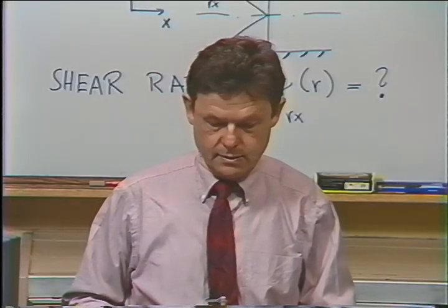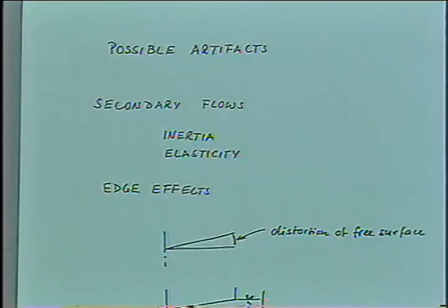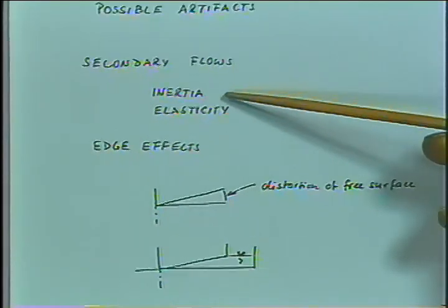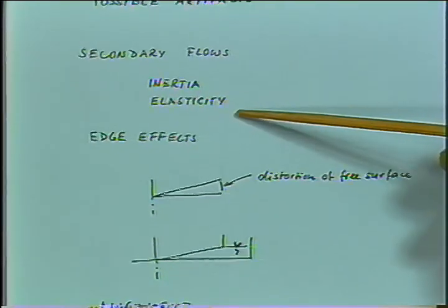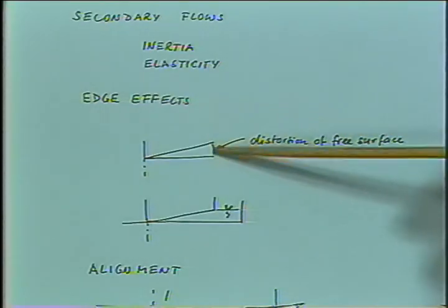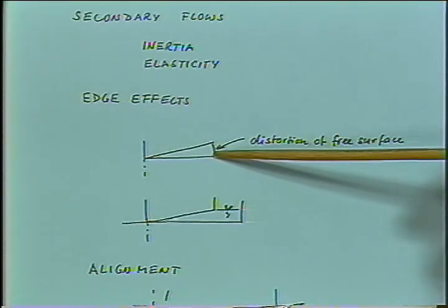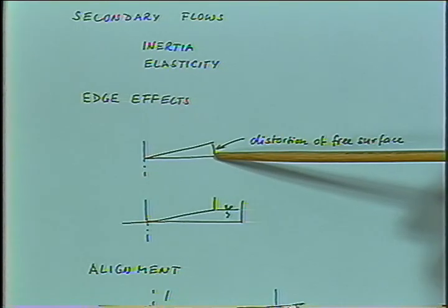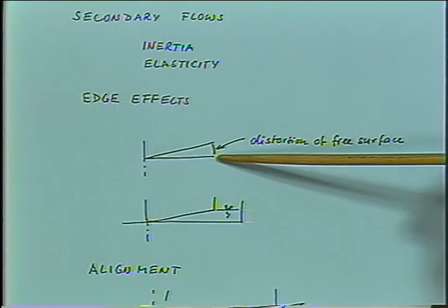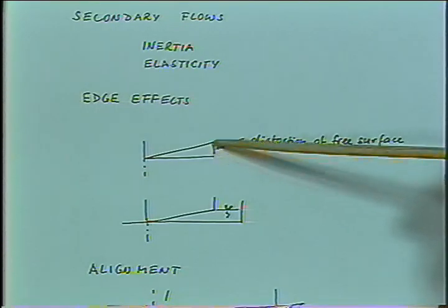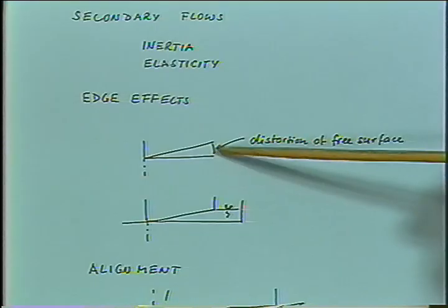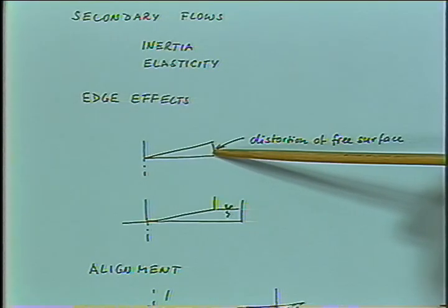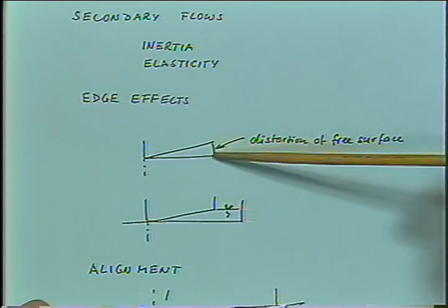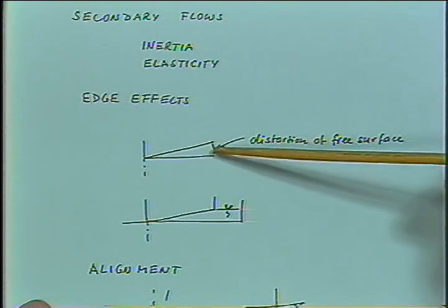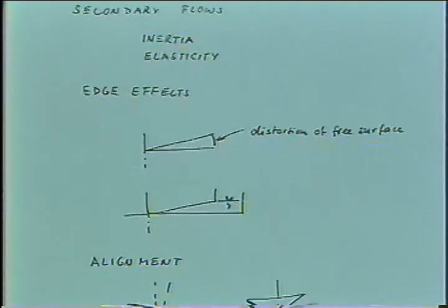The artifacts, just to list them, would be secondary flows, which are due to inertia and elasticity at high rates of deformation. Edge effects: the surface might not be spherical. There might be some lumps on that surface, and you will pick that up especially in your normal stress measurements. If there are fluctuations over here, you will see fluctuations in N1. At large strains, when you put in maybe several rotations, this surface might not look as nice anymore, and then your data are falsified just by the presence of this free surface.